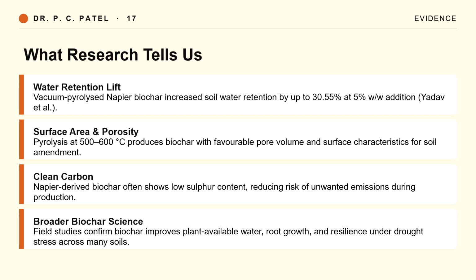What research tells us. Water retention lift: vacuum pyrolyzed Napier biochar increased soil water retention by up to 30.55% at 5% weight addition, Yadav and his co-workers. Surface area and porosity: pyrolysis at 500 to 600 degrees centigrade produces biochar with favorable pore volume and surface characteristics for soil amendment. Clean carbon: Napier-derived biochar often shows low sulfur content, reducing risks of unwanted emission during production. Broader biochar science: field studies confirm biochar improves plant available water, root growth, and resilience under drought stress across many soils.